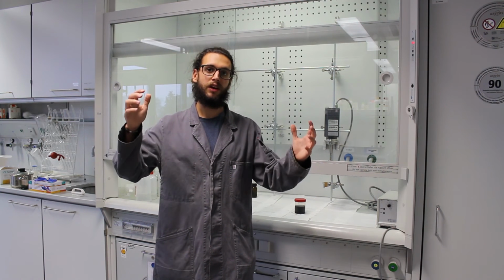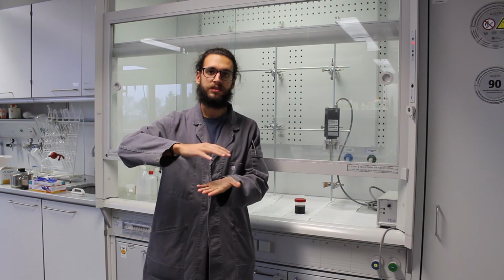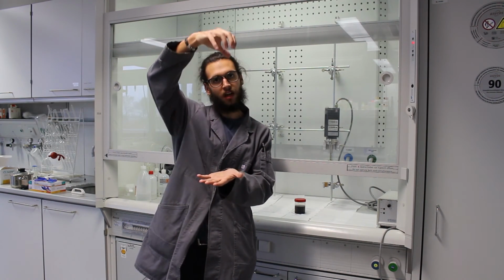Why? The thing is that due to the way that nanotubes are processed, it's called chemical vapor deposition. Basically, you have a very, very warm gas rich in carbon, which deposits carbon atoms on a substrate. So the nanotubes grow kind of like in a forest. And because of the way they are grown, they become all entangled. So when you buy nanotubes, you are not really buying tubes, you are buying agglomerates of nanotubes. So once these agglomerates are broken, you are able to get single nanotubes.